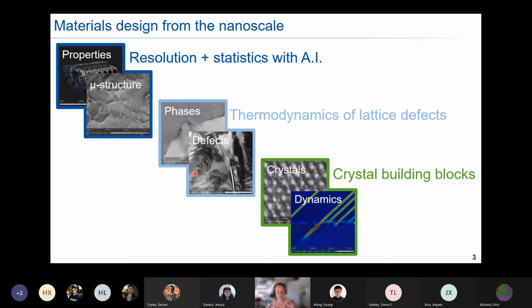At the macroscopic scale or at the microstructural scale, there's a problem we wanted to address in that most of the time you have very heterogeneous alloys. High performance alloys are intrinsically heterogeneous, and what we always get is that we get to high resolution, but then we're missing the statistics, and that's something we've tried to address using convolutional neural networks. I'd also want to go down a little bit in scale and tell you briefly how we try starting to think about thermodynamics of lattice defects. So not just their structure, but also their thermodynamics.